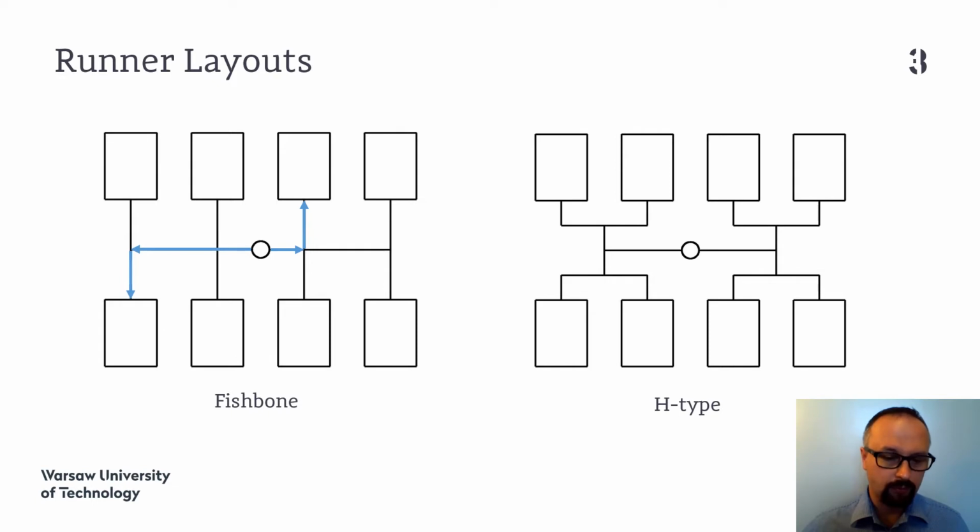from the sprue to the different cavities is not equal. The length is different. We can see clearly here that the length of the first cavity is much shorter than the length of the flow path to the last cavity, and that's of course the reason for mold filling imbalance if we are not making any kind of so-called rheologically balanced runners, so without changing the diameters of the runners, of the gates, and so on.